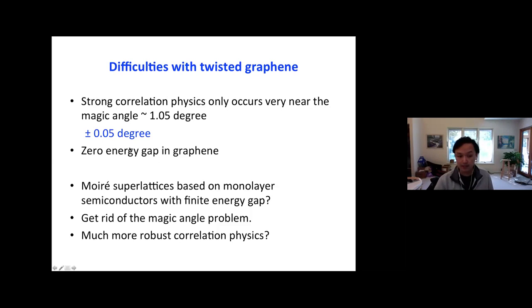So our question is, can we build moiré superlattices based on monolayer semiconductors? Can we get rid of the magic angle problem? We call it a problem because we don't want it to be that sensitive to twist angle. We hope that with a wide range of twist angles, because typically in the material we have disorder in the twist angle, we can get rid of this magic angle problem and get much more robust interaction physics or correlation physics.